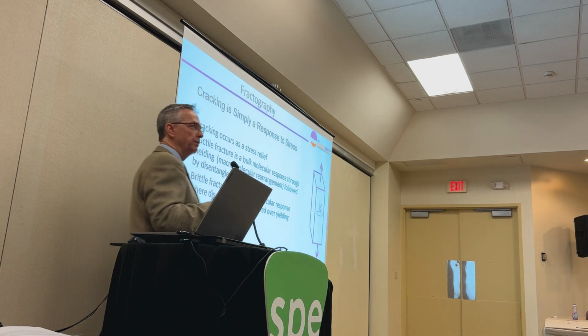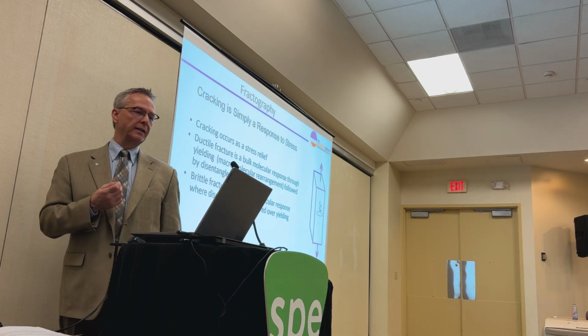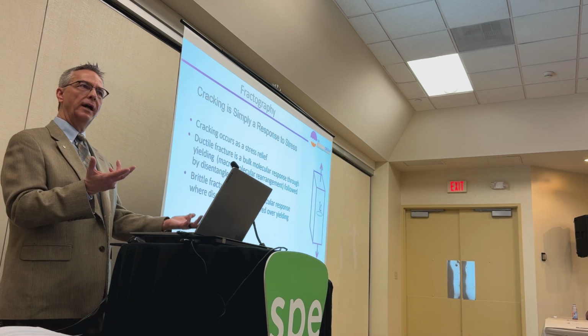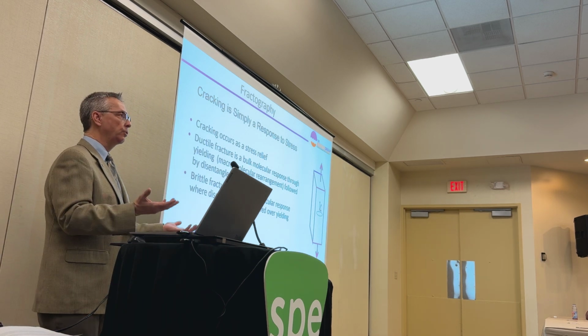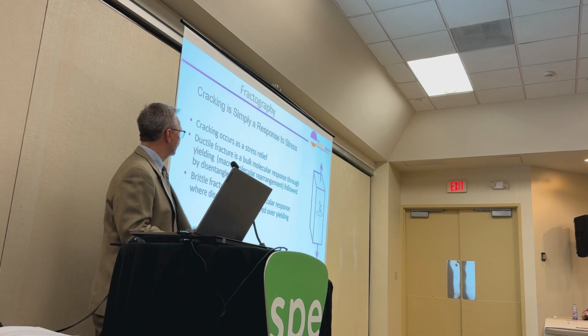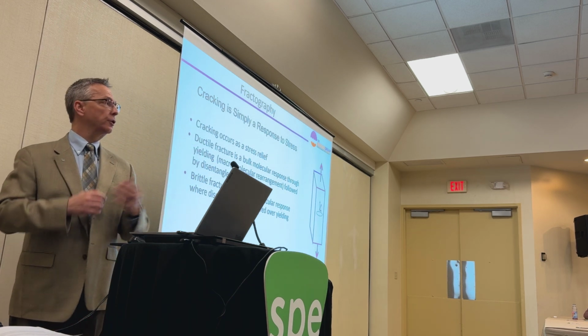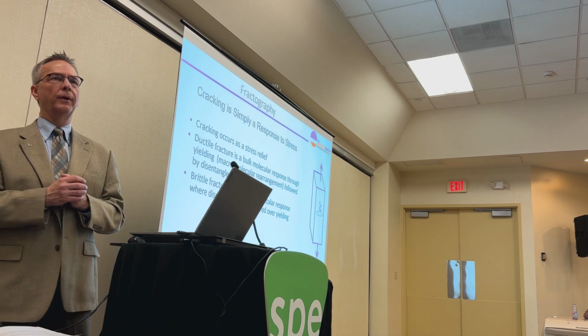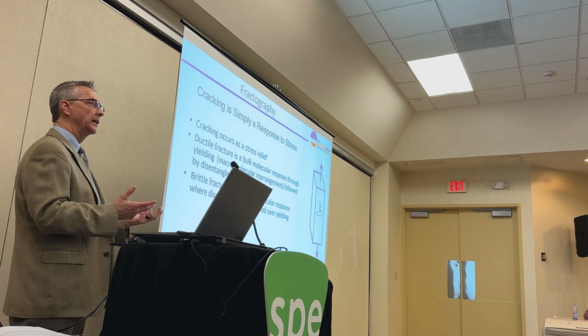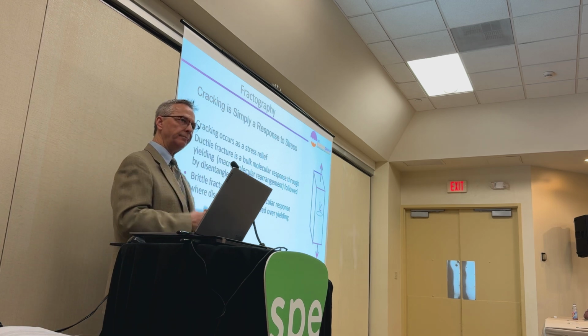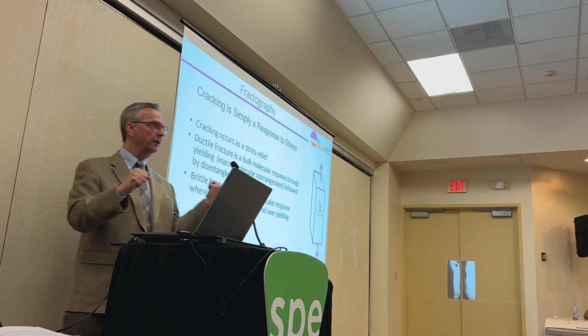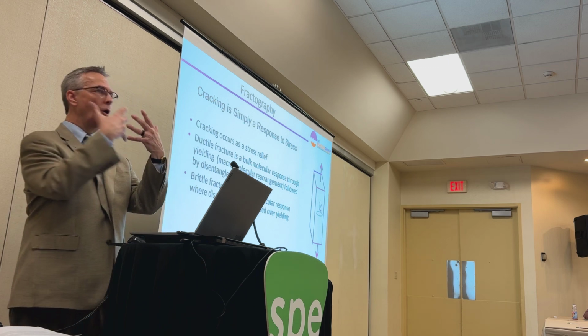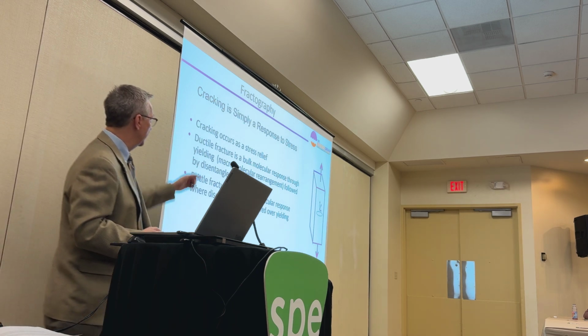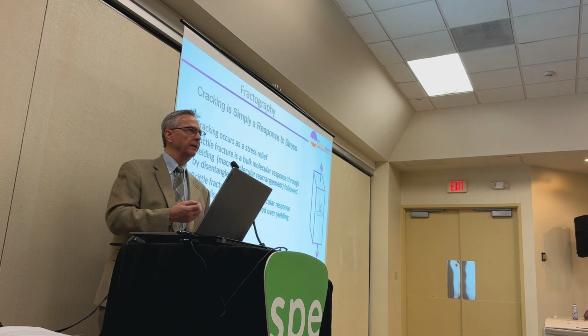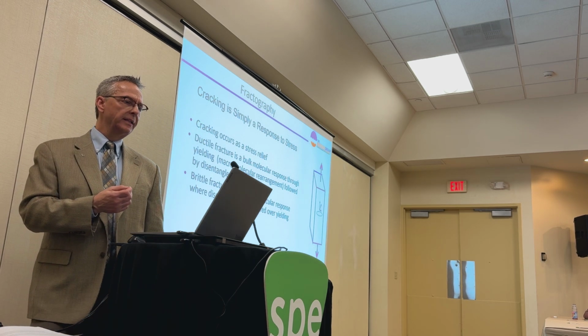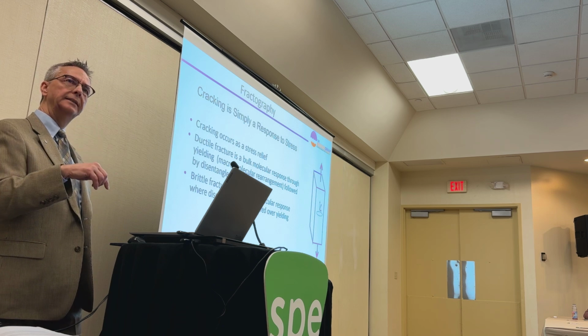So again, what we're looking for are the features that are present on that fracture. Thinking simplistically, cracking is a response to stress. It's a stress relief mechanism. Our part is under stress, it doesn't want to be under stress, so it cracks to relieve that stress. We can have a ductile fracture, which is a bulk molecular response that occurs through yielding. So a macromolecular rearrangement followed ultimately by disentanglement, because that's how plastic parts break. Those molecules disentangle. We don't break the covalent bonds that hold those chains together. It's all about disentanglement. Or we can have a brittle fracture, where we skip the yielding. For one reason or another related to the mechanism, we skip the yielding and we go right to disentanglement.